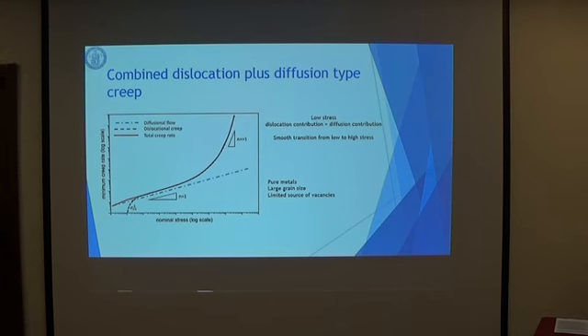We see that at low stresses, it can be that the dislocation contribution is greater than the diffusion one, and there is a smooth transition going from low to high stresses. This condition is typical for pure metals having large grain size and limited sources of vacancy.